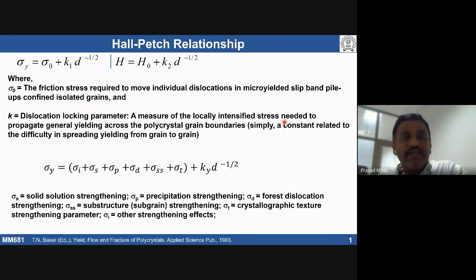It is a very interesting equation developed based on experimental findings, where Hall and Petch, two scientists, within a 2 year span of time, made observations on iron when it was deformed at different grain sizes, and established how yield stress varies with grain size. The equation they arrived at from experimental findings is basically: stress is proportional to the inverse of the square root of d. This is the governing equation proposed by both Hall and Petch simultaneously, and within a 2 year span, both of them came up with this relationship. That's what people call the Hall-Petch relationship.